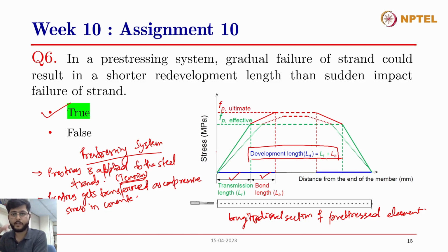If there is a failure of the pre-stressing system, the pre-stress in the strands gets released. It gets reduced due to, let's say, elastic shortening, or due to loss of pre-stress over time, due to creep and relaxation. Also, these different types of failure, or due to deterioration of the strands, maybe due to corrosion also. So the effective pre-stress in the strands gets reduced, and therefore the development length required for the effective stress to be transferred to the concrete increases.